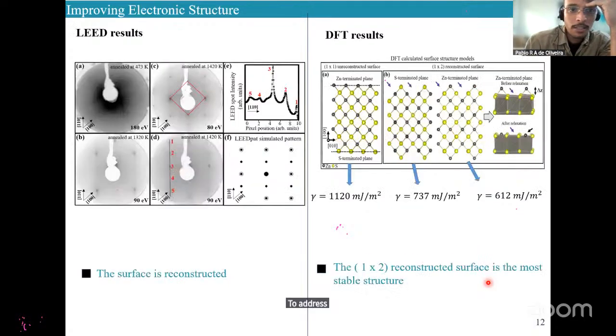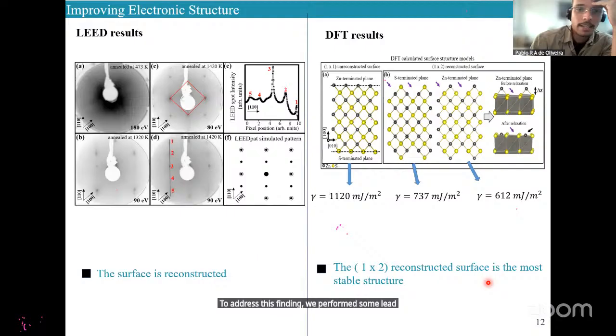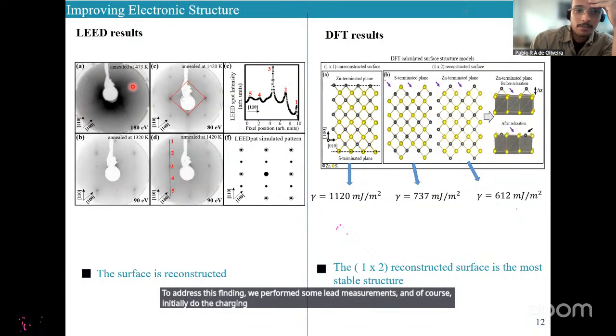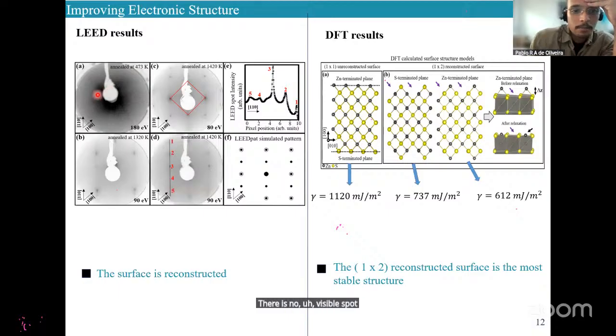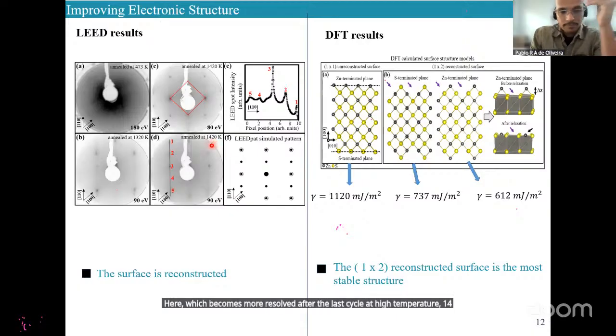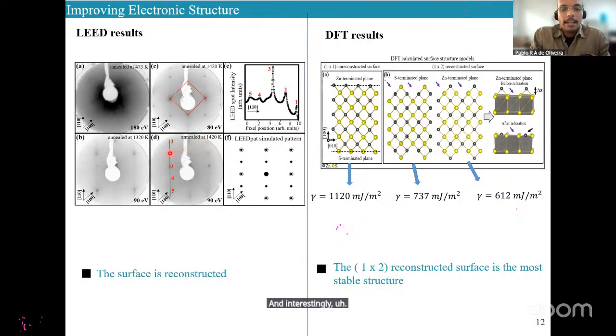To address this finding, we performed some LEED measurements, and of course, initially with the charging effect, there's no visible spot. But as you increase the temperature, we start to note blurry, not well resolved spots, which become more resolved after the last cycle at high temperature, 1420 Kelvin. And interestingly, we can note the extra point in each row, which is detected by this line profile plot here, confirming the existence of 5 points in each row. And this pattern aligns well with the (1 x 2) surface reconstruction.